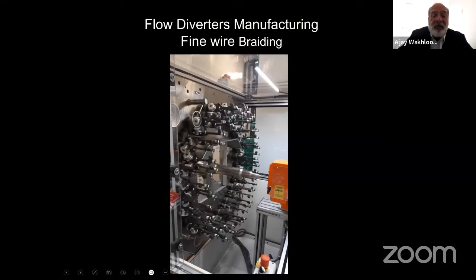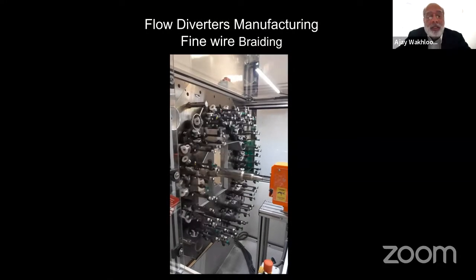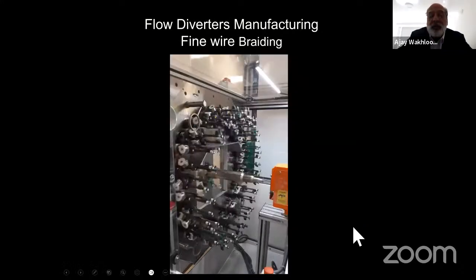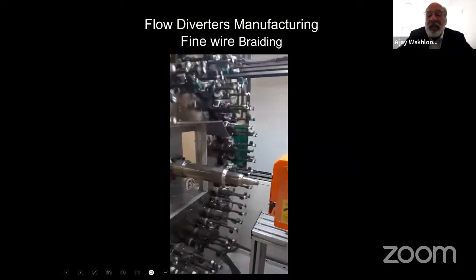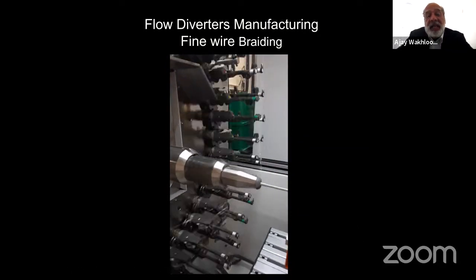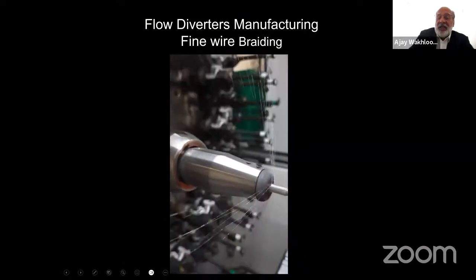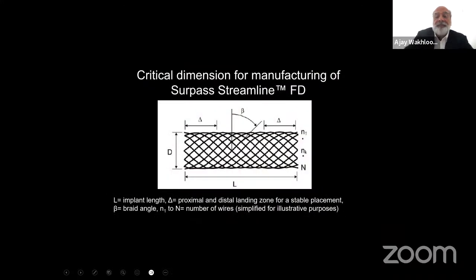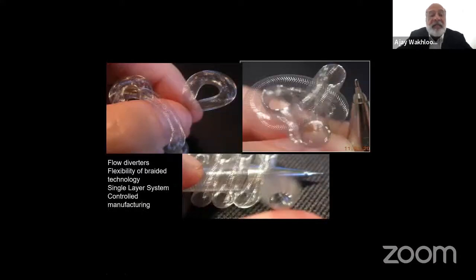And then with that said, we moved into the field of braiding, because braiding was the easiest way to basically create these implantable devices. And you see one of the large braiders here illustrated in this videotape. So what we did is we created a single layer braiding, because the easy thing about single layer braiding is that you can control a lot of different parameters which otherwise are uncontrollable.